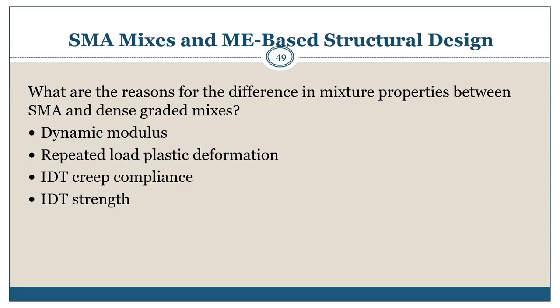Indirect tensile creep compliance values for SMA mixes generally exhibit more compliance because of the higher asphalt contents and the use of fibers, as well as polymer modified asphalts. Higher compliance values are more resistant to thermal fracture. Indirect tensile strength of SMA mixes, however, is generally lower in comparison to conventional dense graded mixes, generally because of the higher amounts of asphalt. The creep compliance values, however, generally control the resistance to thermal fracture, or creep compliance is more important than strength by itself. The differences between the mixes are going to be illustrated in the next few slides in terms of laboratory measured values.